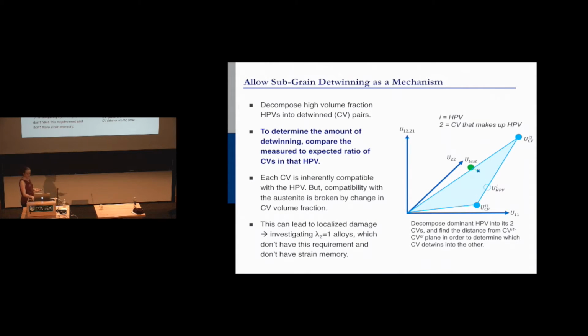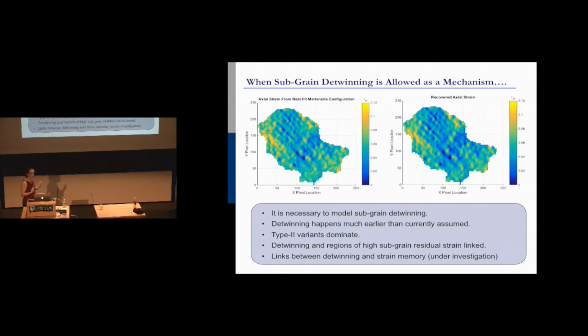And when you do that, and you predict the variant pairs that are going to arise because of detwinning, then we can match the high strain regions. It's the only possible way that we can match high strain. There was no other way to do it. There was no combination of variants that matched with a perfect habit plane that we could use that would explain what we were seeing experimentally.